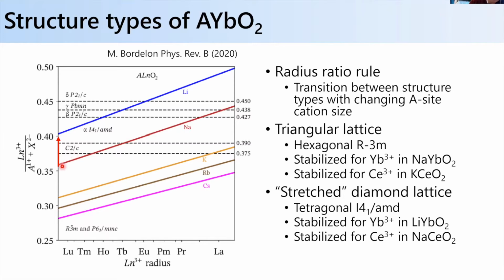So basically, if I was just looking at the line with ytterbium, if I start with sodium, then I get the triangular lattice. But if I want to switch, I can switch the sodium to lithium and I'll get the diamond-like lattice, okay? And this is nice, Mitchell is a chemist at heart, so this is a nice radius ratio rule he came up with. And so this motivates why we chose the chemical formula we did to try and stabilize both the ytterbium and cerium-based compound for each of these two different lattice types, okay? So it shows you why we have to swap out the A site as well if we're going to keep the chalcogen site stuck on oxygen.